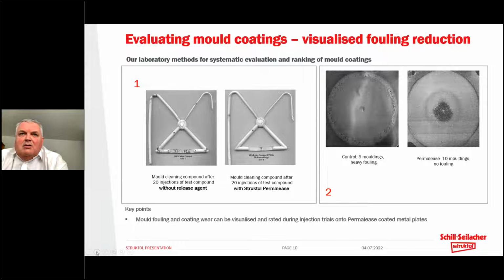deposits there. By contrast, the spider molding alongside it is 20 injection cycles of the same compound onto a mold coated with a very effective release agent, one of the products from our Struktol Permalease range. And we can see for the same number of injection cycles, far less in terms of dirt deposit.